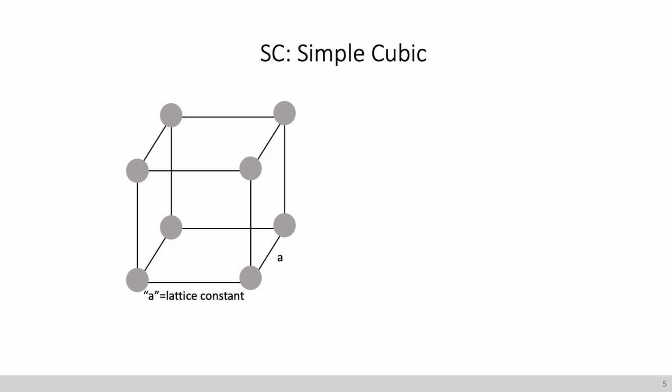The first calculation that we're going to do for simple cubic is find the total number of atoms enclosed within the cube. So when we say enclosed within the cube, we want to find the total volume, what total fraction volume is enclosed within the cube in order to calculate the total number of atoms enclosed. And so to do that, we observe that each corner is intersecting 1/8 of the atom sphere, and we approximate the atom as a sphere.